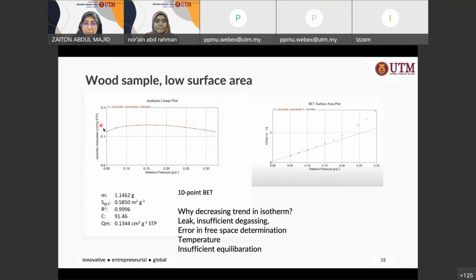So possibly what happens here, there might be a leak. There might be insufficient degassing in the sample preparation. Remember, in the sample preparation, you have to degas, right? You have to throw out all the impurities. There might be insufficient degassing. There might be a leak. There might be error in the free space. You don't have enough sample. The temperature is not correct when you did the degassing. And insufficient equilibration, that means the samples have not reached equilibrium. This could be due to error in the free space or incorrect temperature. Because the C value is okay, positive here, but then you have this decrease and deviation from the linear range in that region of 0.05 to 0.3. Okay, so this is an example.